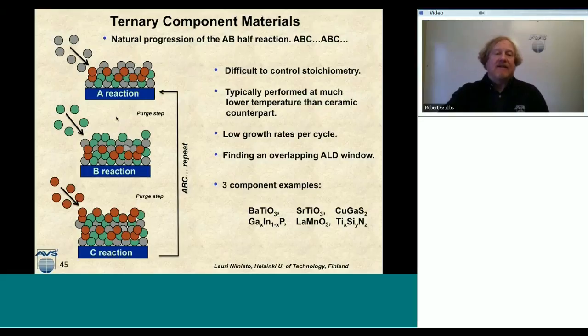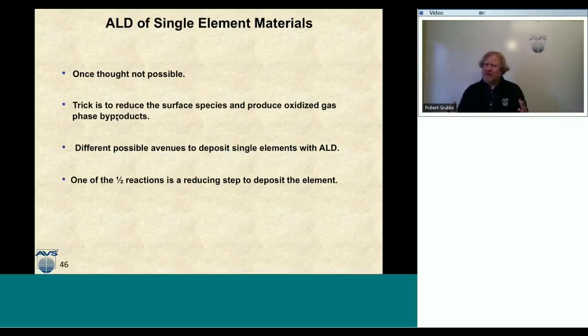Now let's talk about single element materials. Single element materials were once not thought possible because AB cycles in ALD would put down a metal oxide or metal nitride. So how do you put down a single element using ALD chemistry? The trick is to reduce the surface species to produce some sort of oxidized gas phase byproduct and reduce that element on the surface down to its zero oxidation state. There are different possible avenues with single element ALD, and I'm going to go over four of them. We'll notice that always one of the half reactions is a reducing step to deposit the element onto the surface.